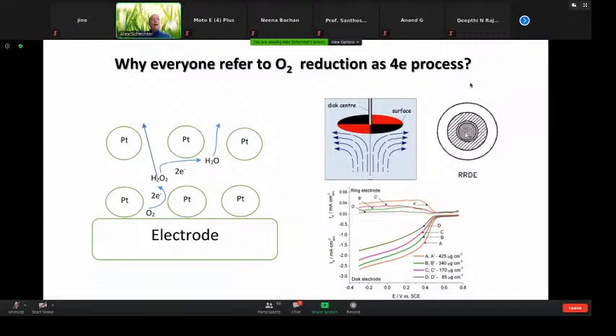But this is a macroscopic kind of analysis. And the reason is because when doing it, we're placing a thick layer of platinum, many billions, trillions, who knows how many, of catalysts on the surface, one lying on top of the other. And as you do that, if the peroxide is formed, say, inside that layer, it can continue to react within the layer. So eventually, what comes out is only water, not peroxide. You make hydrogen peroxide from oxygen. The hydrogen peroxide can further react on platinum and goes out as water. So practically, everyone measures just water with very little peroxide.